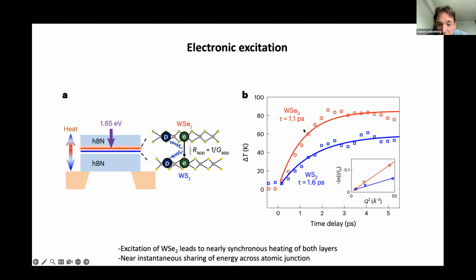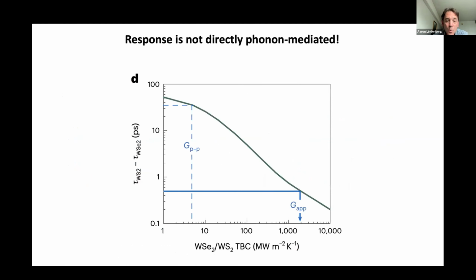Okay, and so now here are the experimental results. Again, change in the temperature for each layer as a function of time, but now the time axis is increasing on 1 picosecond timescales. So rather than hundreds of picoseconds, you can see the two layers essentially heat up almost concurrently, essentially synchronously, within of order 1 picosecond. Okay, and so this is saying that even though we've deposited all of the energy initially into the WSe2, the energy is shared between the two layers and they largely equilibrate within a couple of picoseconds. Okay, so what's the mechanism and how do we understand what's going on here?